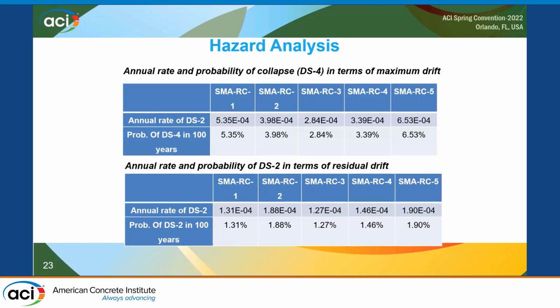And this table summarizes 2 different types of damage states. One is damage state 4, that is collapse. And from the figure, we can see that all the bridge piers had a very low probability of collapse in terms of damage, with SMA-3 having the lowest probability of 2.84%. And if we look at damage state 2, for which the bridge piers were designed, again, we can see that these had very low probability. Again, SMA-3 performed best in terms of damage probability.